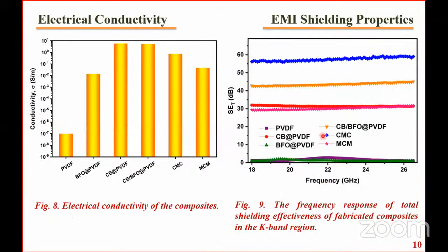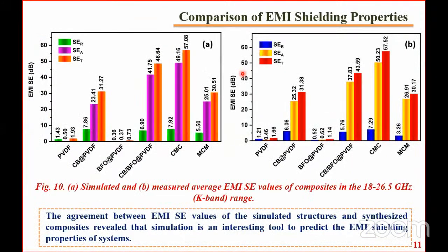From the electrical conductivity study, it is clear that even though the CMC composite exhibited a lower conductivity than the conducting magnetic PVDF and carbon black PVDF composites, the CMC composite exhibited superior shielding behavior, as expected from the simulation studies. Also, the simulated and measured values are in agreement with each other, as we can see that it is 57.08 dB here, and 57.52 for the measured value. The agreement between the EMI shielding values of the simulated structures and the synthesized compounds reveals that simulation is an interesting tool to predict the EMI shielding properties of systems.